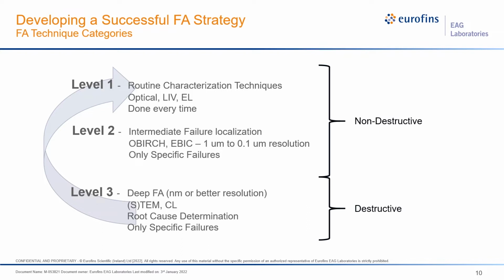And then from the information that we get from that first set of data, some samples will be interesting enough that we want to look a little bit closer and do some intermediate failure localization. So this is level 2 type work. This is something where we're going to hopefully isolate the failure to within, let's say, a quarter of a micron resolution. So we're going to utilize techniques such as optical beam induced resistance change, a scanning laser technique called OBIRCH, as well as electron beam induced current, which is an SEM technique. And we're only going to do this on specific failures that maybe are unusual or we don't quite understand from the level 1 characterization.